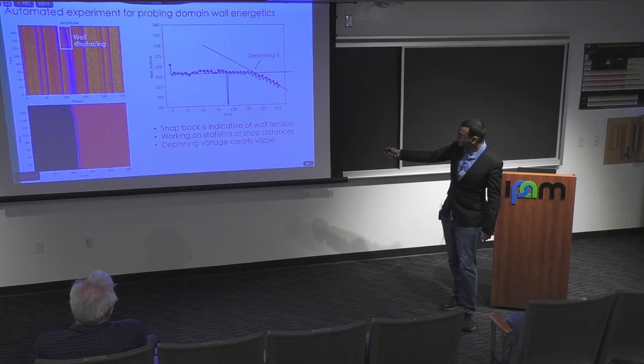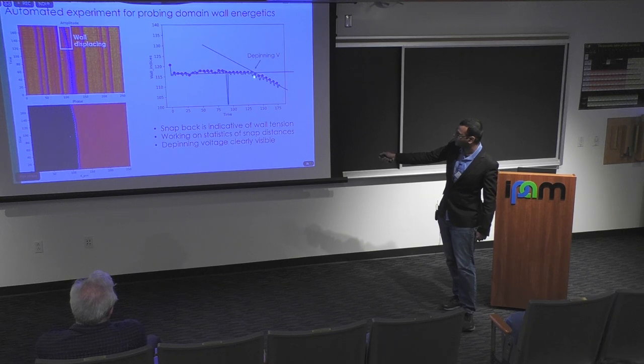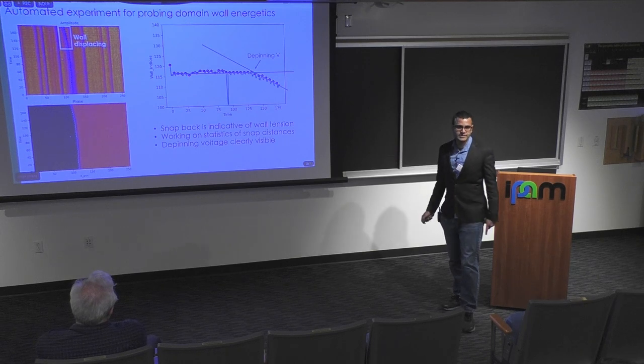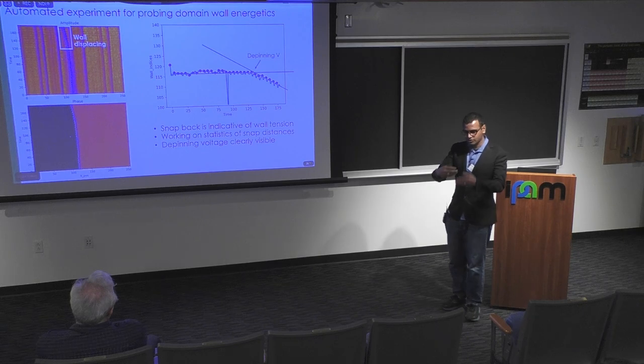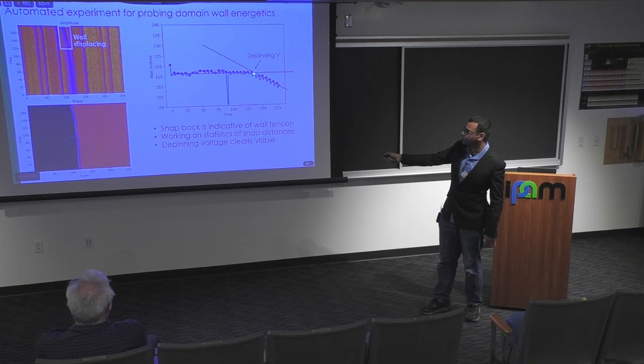But there's another very interesting thing that you're seeing: after we apply a voltage, you can see the wall snapping forward and then snapping backwards. So why is this happening? The reason is that the wall is an elastic interface, and as you apply a voltage, the wall deforms a little bit, but this deformation results in some tension on the wall. In order to reduce the elastic energy, it will try to snap back, but it snaps back to a slightly new equilibrium configuration, and that's exactly what you measure here.